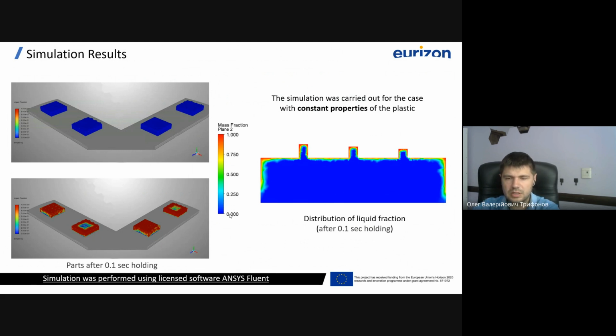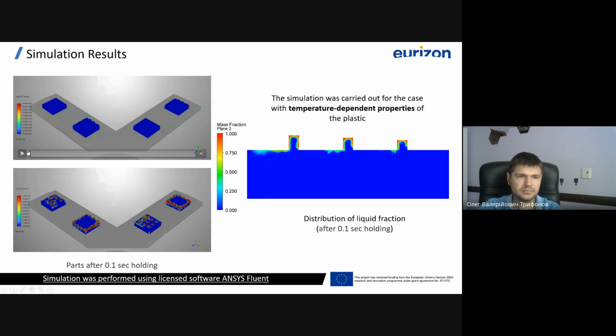But after applying temperature-dependent properties, we see a bit different picture, and we have found that the process of melting is not so fast, and within the same time we can see that melting takes place only on the bars and small elements of the parts. Once more, it means that temperature-dependent properties sufficiently influence the simulation result, and we observe approximately the same picture in experimental investigations, which will be presented in our further articles and publications.